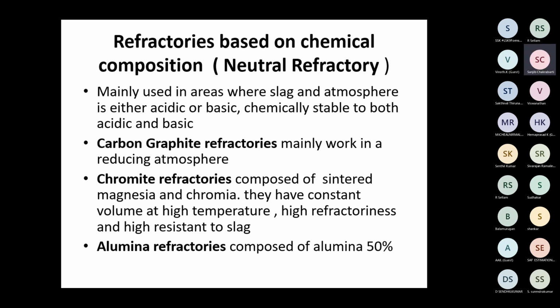Then chromite refractories, composed of sintered magnesia and chromia. They have constant volume at high temperature. This is a very good but very costly refractory. The volume stability is very high for this refractory. Alumina refractories, composed of alumina 50%. High alumina refractory is not neutral. High alumina is usually an acidic refractory.